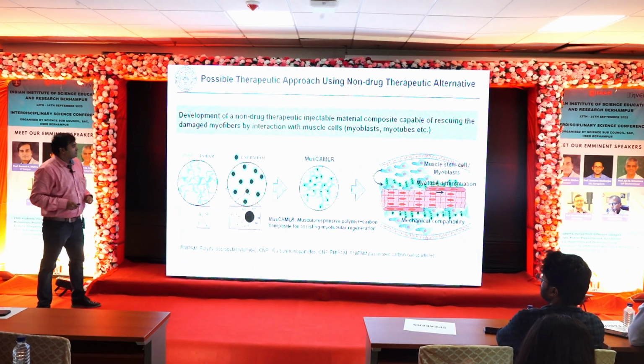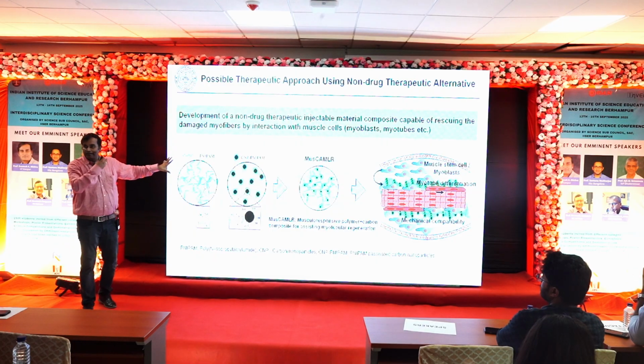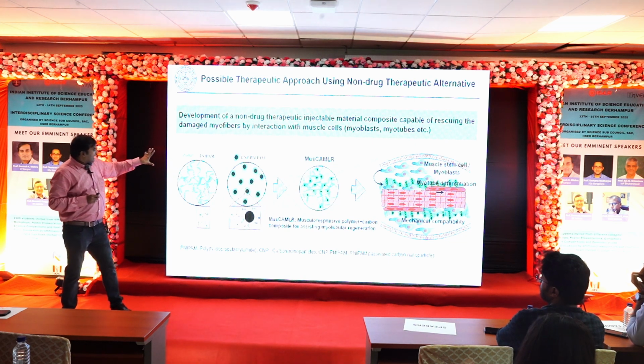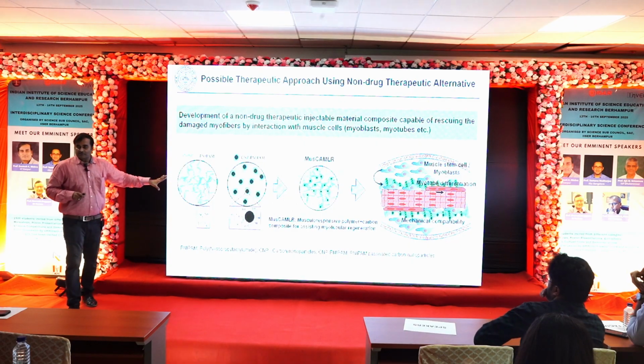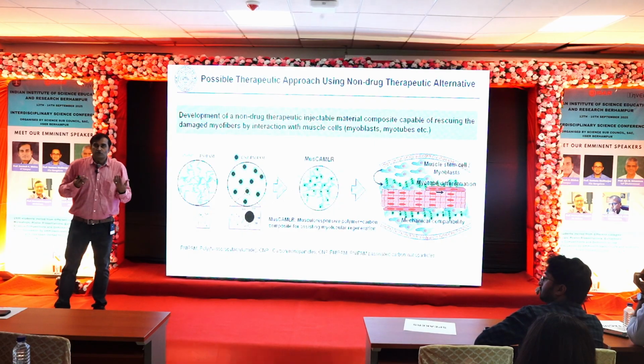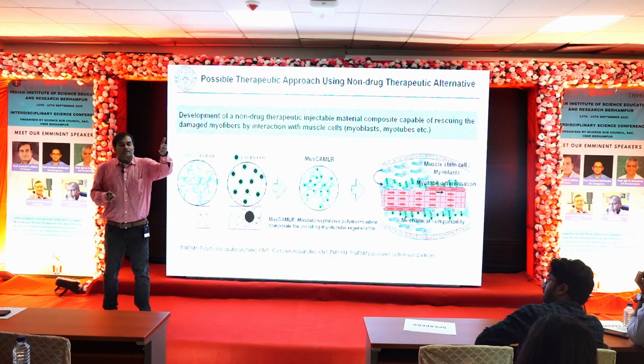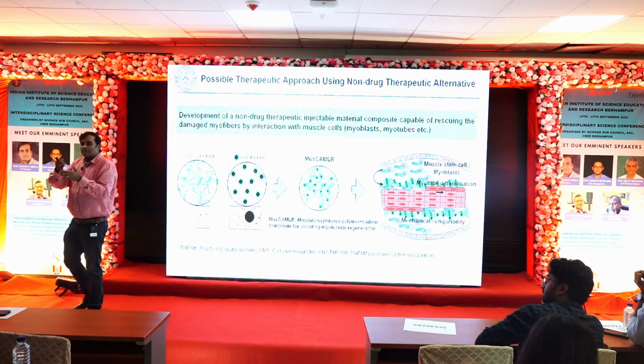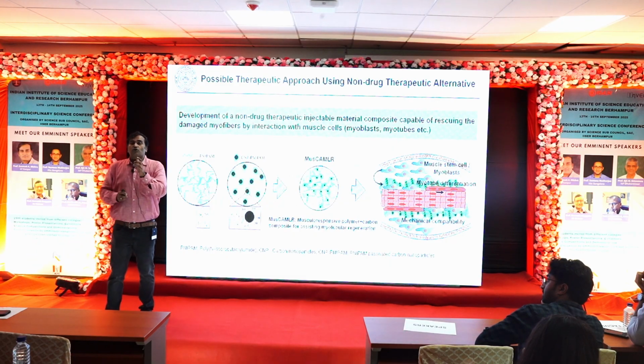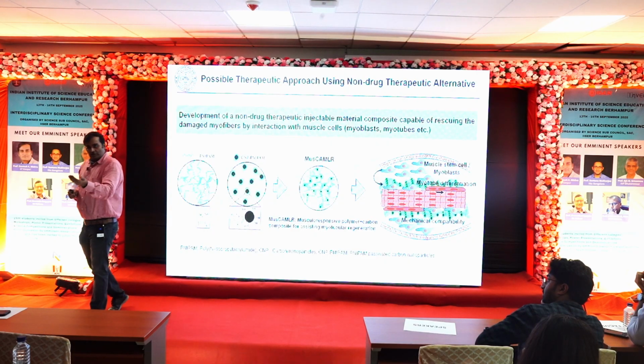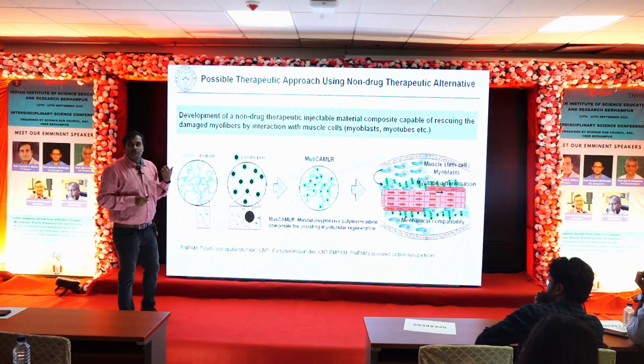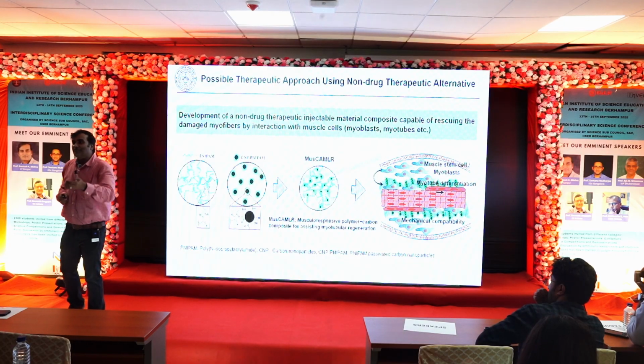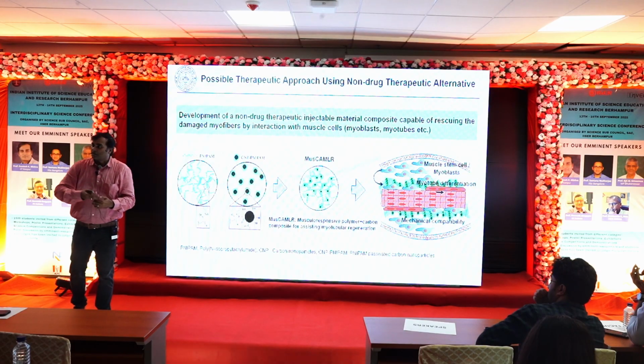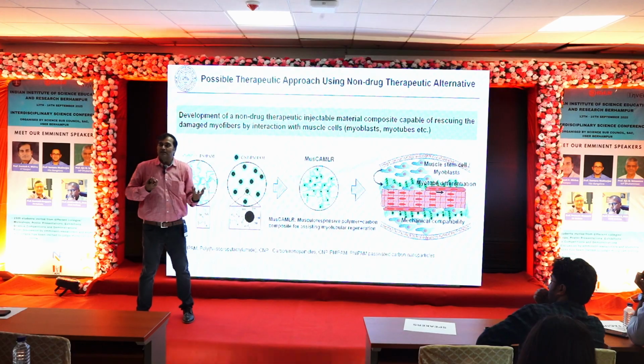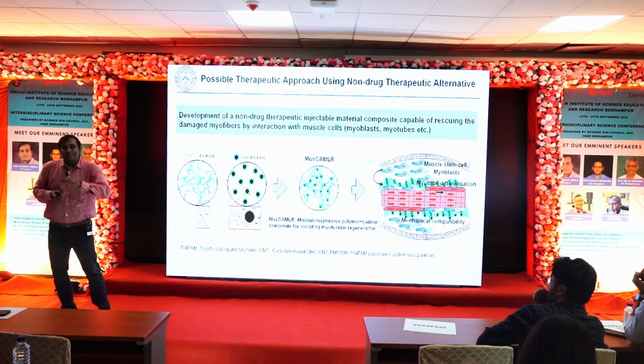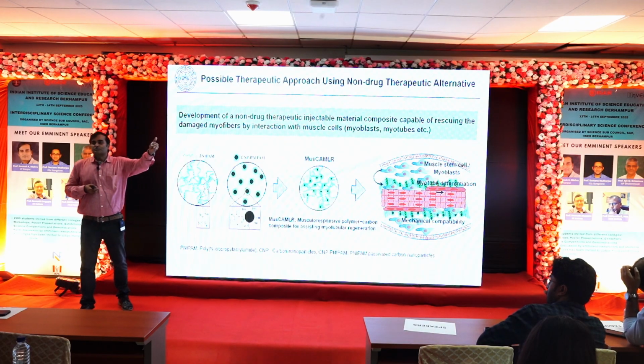How did we do it? We chose a polymer molecule called NIPAM, which is a polymeric system, and we tried to include carbon material in this. And what was the reason? Because this polymer is known to be temperature sensitive, right? At a particular temperature, below that it is in sol or solution phase, above that it is in gel phase, which is a sol-gel transition close to 32 degrees Celsius. That is good because it is below the physiological temperature of 37 degrees Celsius, but it is not good enough, because if any change is happening at 32, at 37 you are not going to see the same change again, because now it is just improving the strength of the material at that particular temperature. So we wanted to increase that critical temperature point from 32 to as close as possible to 37, right?